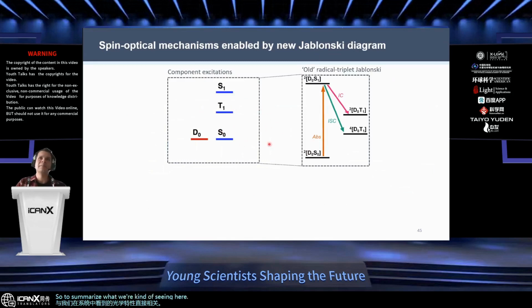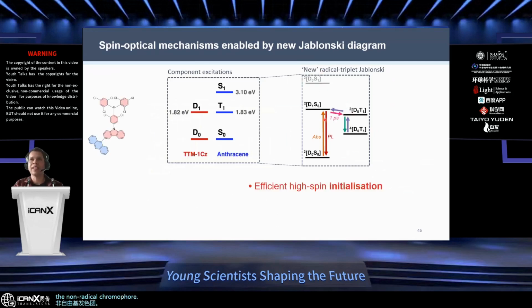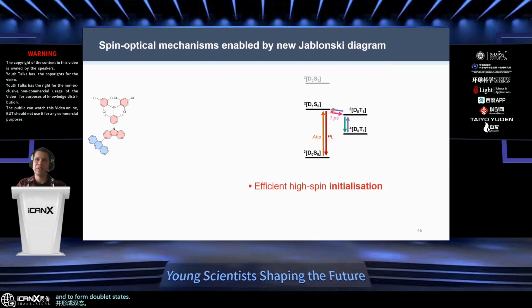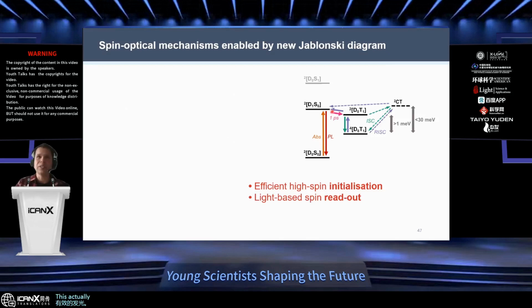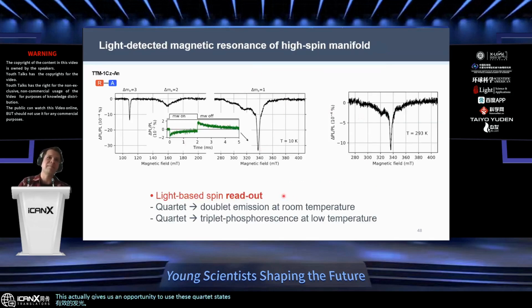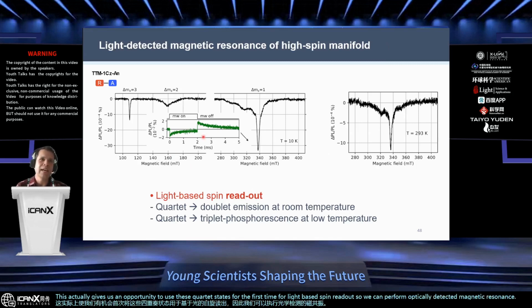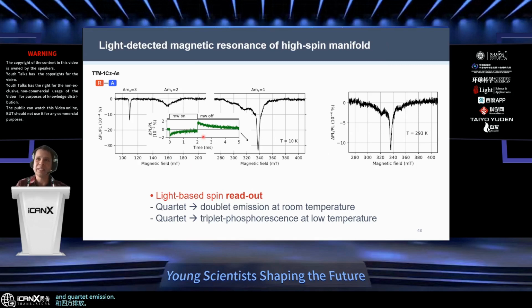So to summarize, whereas before people were exploring the opportunity to create quartet high spin states through the non-radical chromophore, in our scheme we can directly photoexcite to a level which is degenerate with the triplet state in these materials to create high spin states through radical photoexcitation. And these systems not only intersystem cross to form quartet states, but they also reverse intersystem cross to form doublet states with efficient luminescence. This gives us an opportunity to use these quartet states for the first time for light-based spin readouts. So we can perform optically detected magnetic resonance and couple the doublet and quartet emission to the spin state of the system.